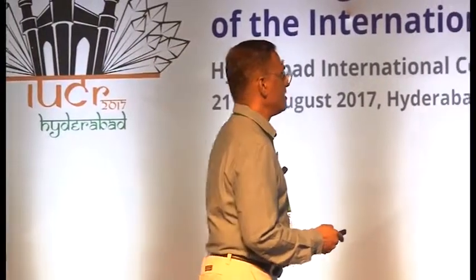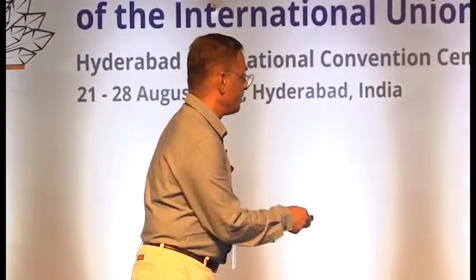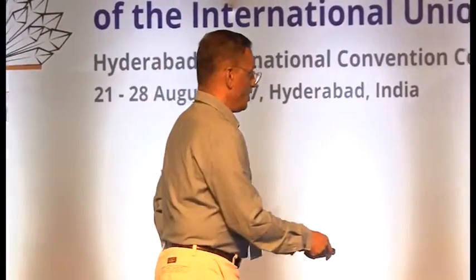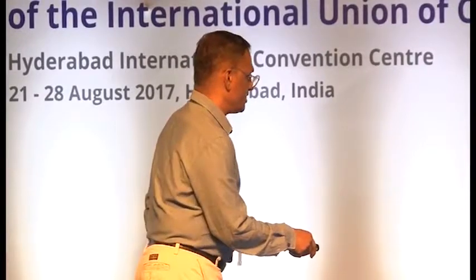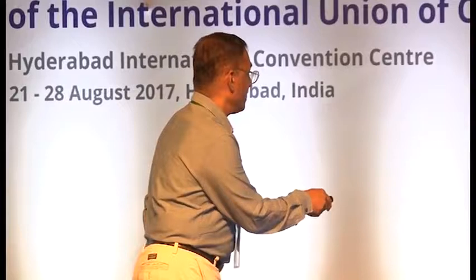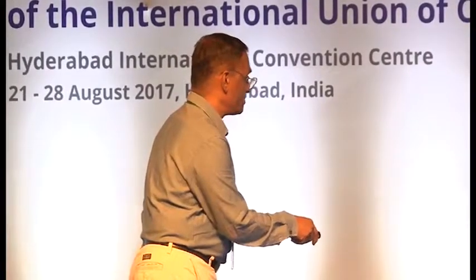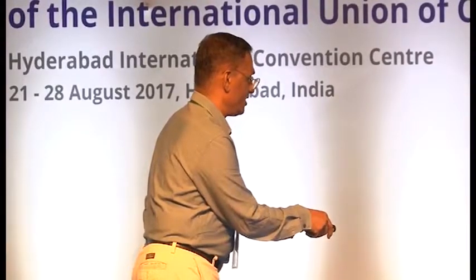Okay, when we were investigating, this is another example from 2+2 cycloaddition reaction. This is a simple metal complex, a dinuclear metal complex with zinc. If you take a look at the packing of this particular compound, you will see that on one side, the double bonds are nicely aligned to undergo 2+2 cycloaddition reaction. On the other side, actually, it's slightly disoriented. In fact, if you just take a look at the position of the methyl group on the benzoate, you see that this is hindering the movements of this. From here, the CH3 is present, so it cannot come closer. Okay, that prevents the 2+2 cycloaddition reaction in this particular compound.